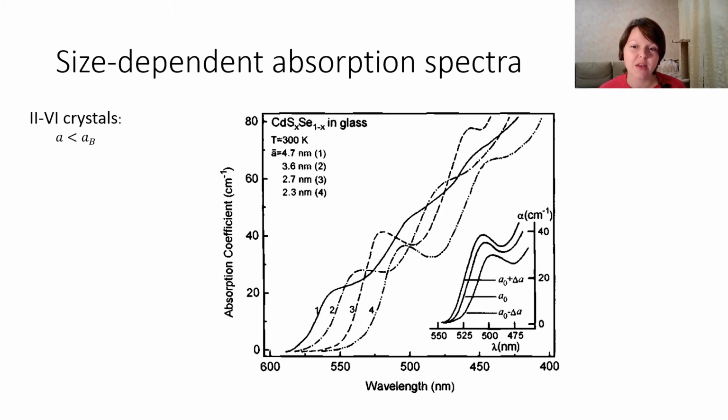It should also be mentioned that the absorption spectra of these glasses are very much alike to the absorption spectra of the commercial glasses that are used as color cutoff filters for the visible spectrum. Here we have the absorption spectra of glass number 1, and by the naked eye it will look like a light red color filter. Glasses number 2 and number 3 will look like orange color filters, and glass number 4 will look like a yellow color cutoff filter.